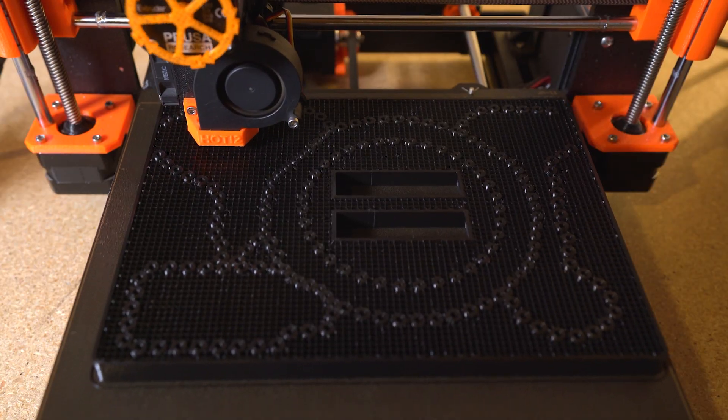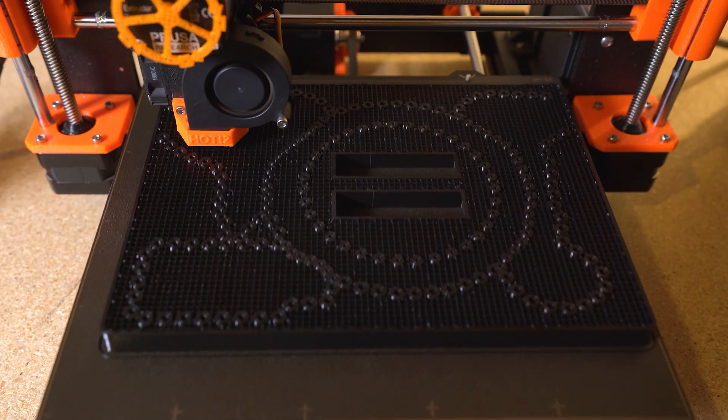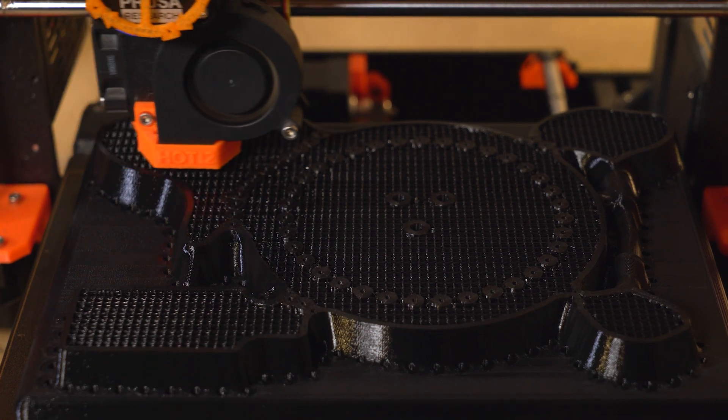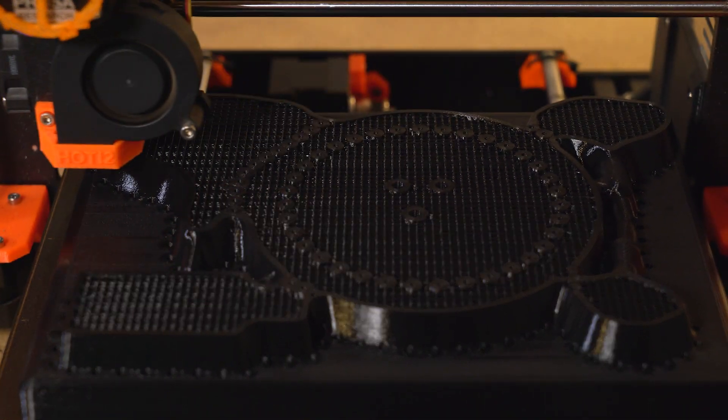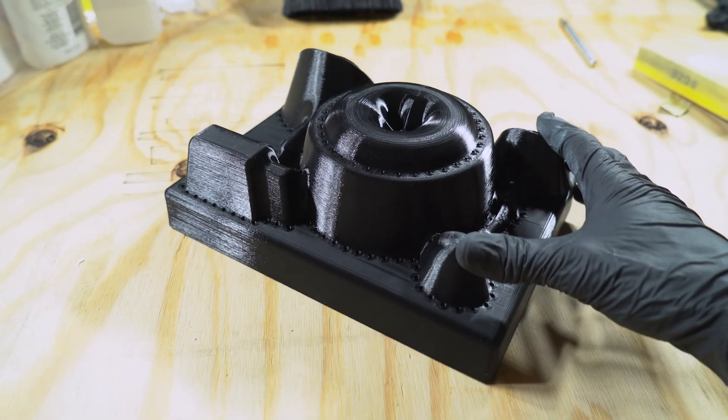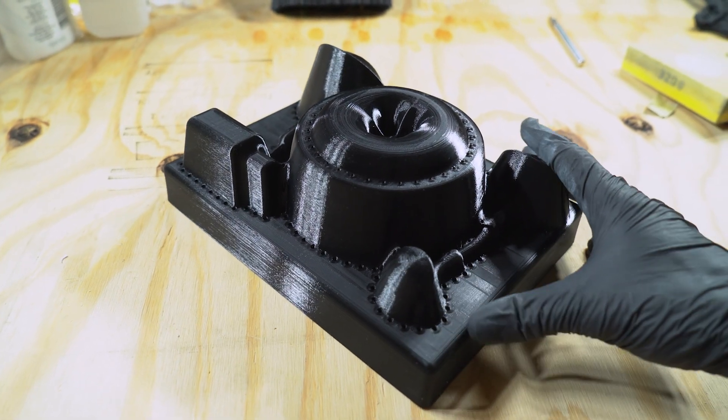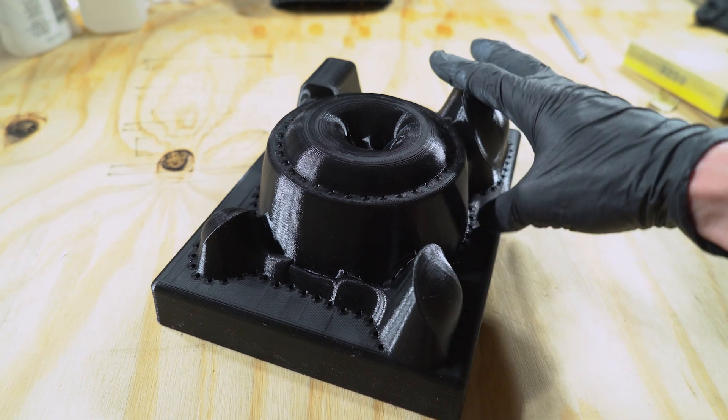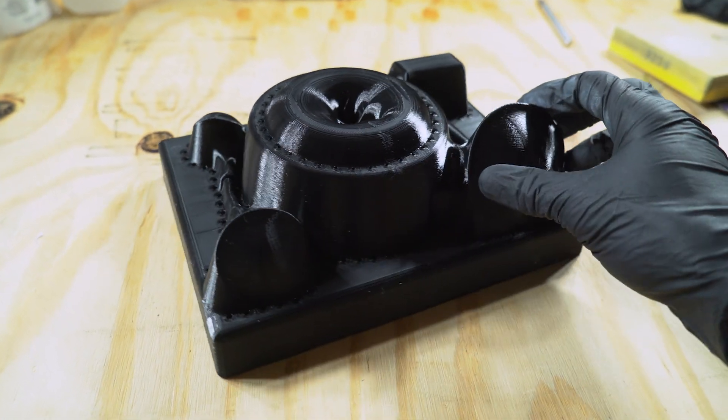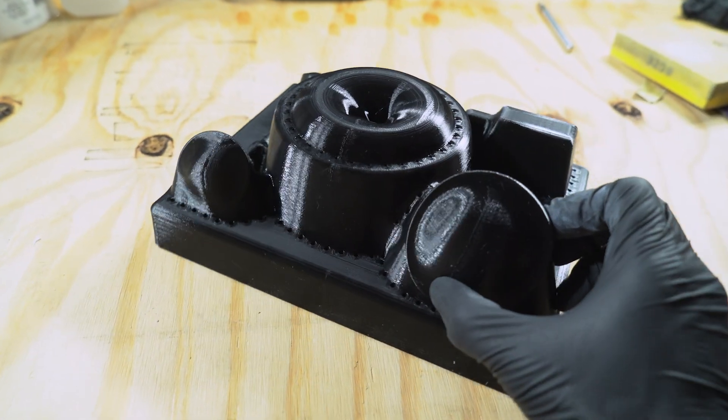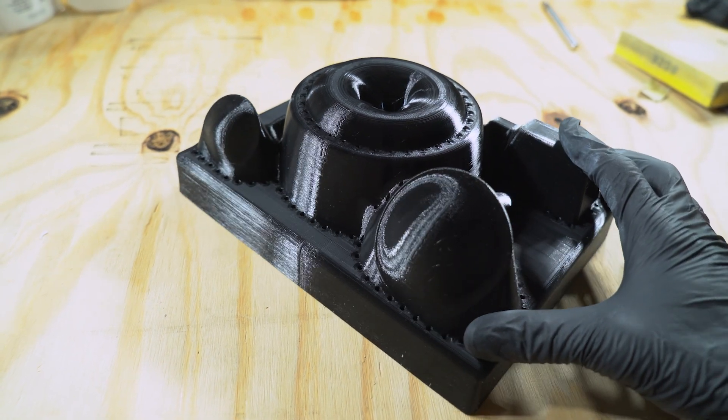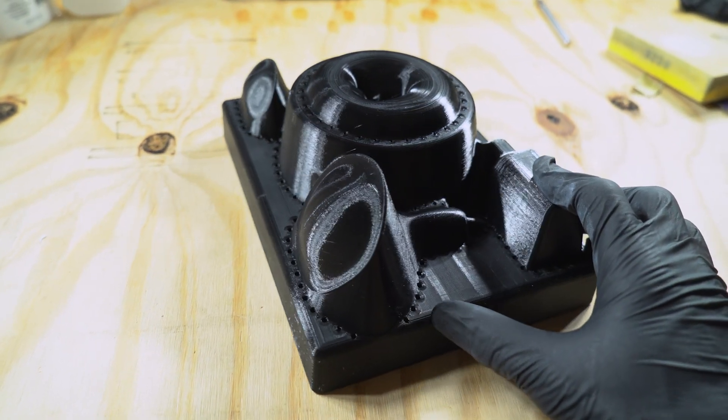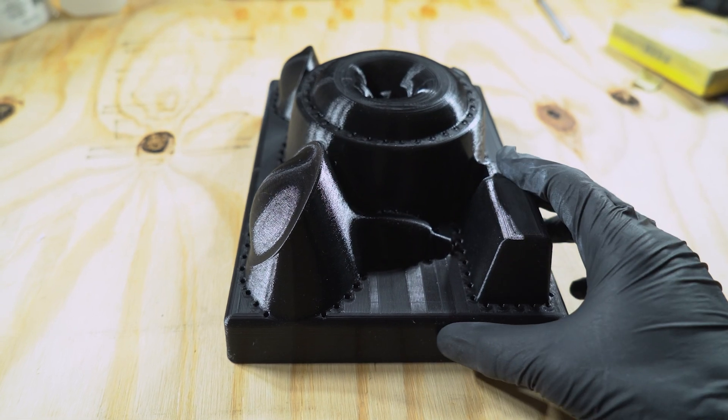With all these concepts in mind, I printed a mold. The wall thickness is 3mm and infill is 15%. This thing took 60 hours to print and weighs almost 1 kilo. I used PETG filament because it can handle higher temperatures than PLA. All of the parts were fully drafted with smooth transitions from one shape into the next with the vents placed at the lowest points.